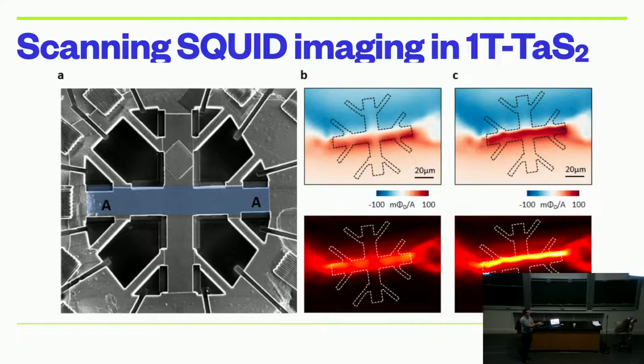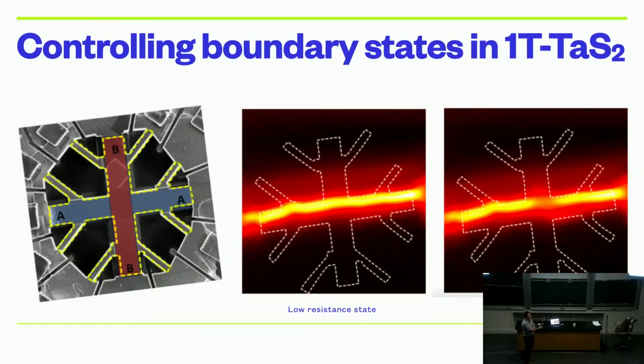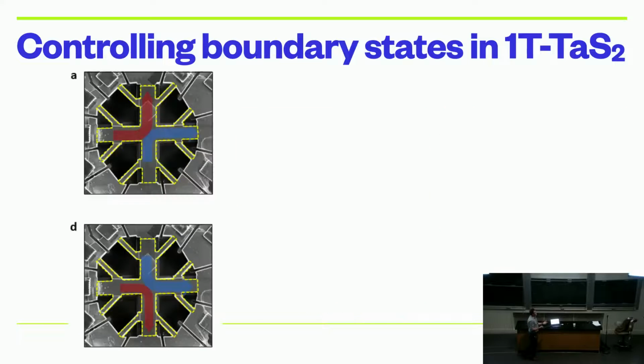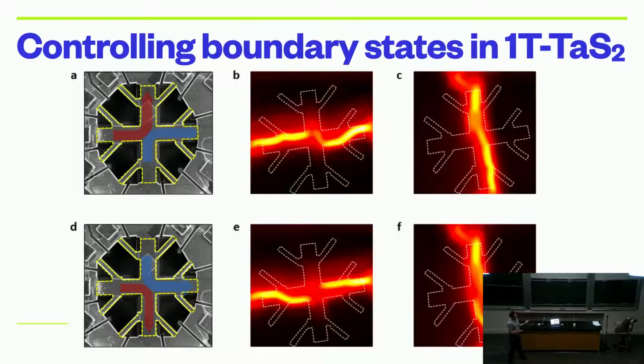So somehow, the boundaries now are carrying the current. So the boundaries of the system near a metal insulator transition are the ones that are driving all of the physics. And if you pulse in the opposite direction, the B direction, you start to see this break up, and the current goes back into the bulk, and you can do this repeatedly. We can even change the direction of the current, and we can control where on the system the boundary is carrying the current, and we can actually switch from what boundary state is carrying it.